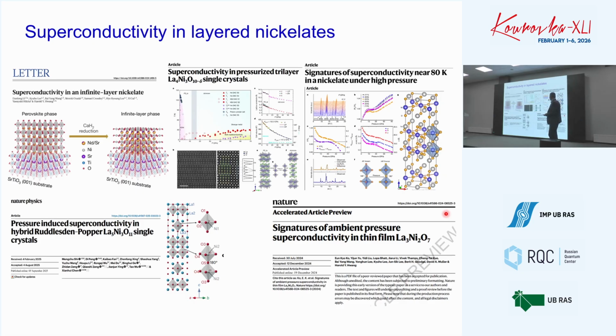In the second part of my talk, I will switch from thin film materials to bulk materials under pressure. This is a very recent achievement made in 2023 or 2024. Many papers were published in Nature, Nature Communications, etc. Some Chinese groups managed to first synthesize really pure, rather than copper-doped, nickelates, and then they realized that under pressure, those materials exhibit quite strong superconductivity. The transition temperature nowadays is about 80 or 96 K.